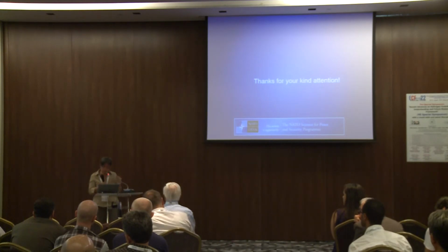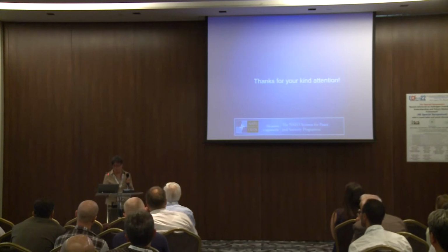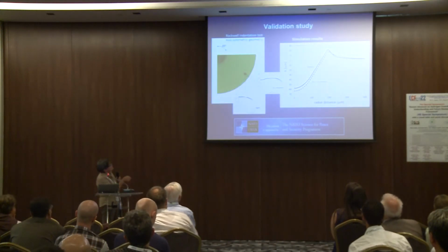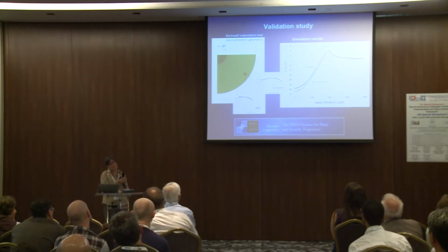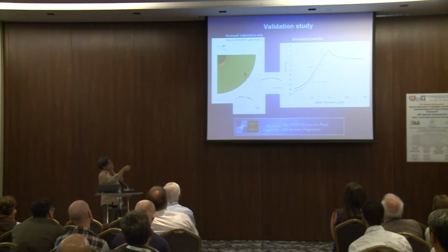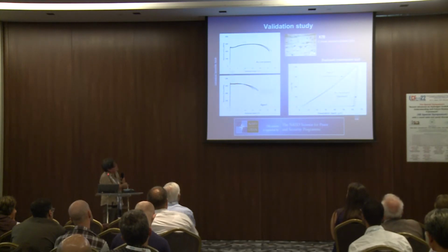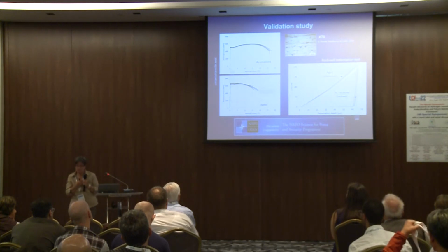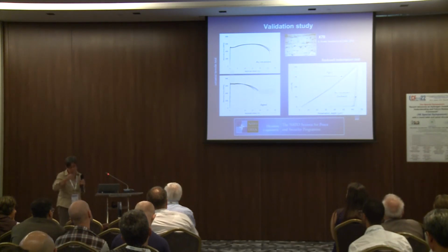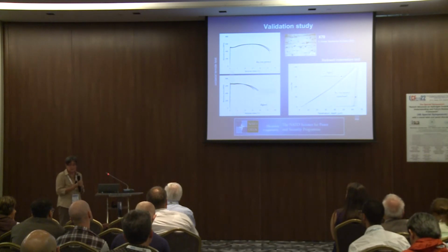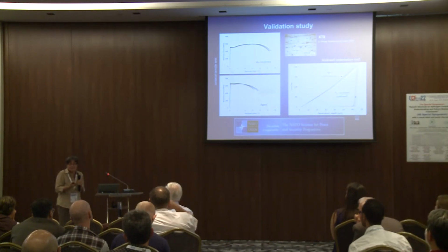And as a matter of fact, to reply to this question, what we decided to do is, for instance, I didn't comment, but what we are using here is a Rockwell indenter, and therefore it is conical but with a rounded tip. And in this preliminary study, which was carried out at 1,200 Newton load, the material was indented, and then there was some micromechanical investigation to see whether any defect was going on. There is nothing happening. And as a matter of fact, it is common practice also to perform hardness tests to check whether the material is in good shape or not. We are doing nothing other than a hardness test on this material.